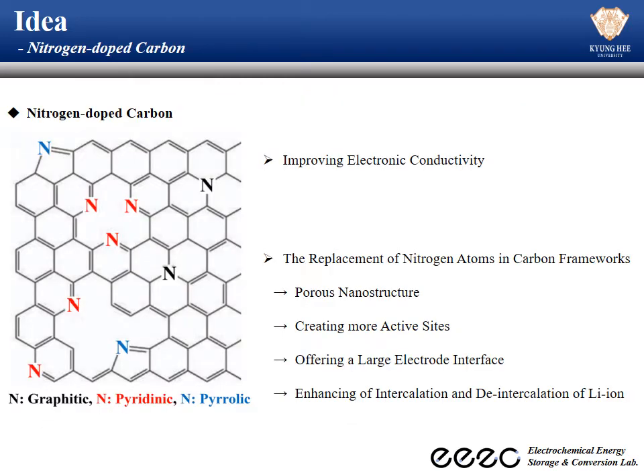Nitrogen-doped carbon was selected as the material for the coating layer. Nitrogen-doped carbon is a form in which nitrogen atoms are doped in the carbon layer, and it is divided into graphitic, pyridinic, and pyrrolic structures according to the nitrogen-doped form. These nitrogen-doped carbons can improve the electronic conductivity, and more active sites are formed due to the porous structure, due to the structure change of the carbon framework by the nitrogen atom. And as the surface area increases, more lithium ions can intercalate and deintercalate in the active material, so it can lead to improved electrochemical performance. Therefore, nitrogen-doped carbon was selected as the coating material for NCA.